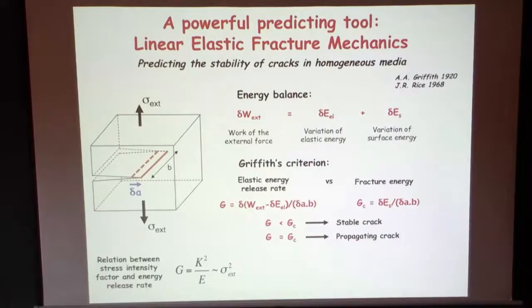Excuse me, why do you call this right hand term dissipation? I mean, if it's just creating the surface, you could regain the energy. Yeah, if we had a real surface energy, you would say, okay, I break the bond, and later on I can bring it back together and recover this energy. Practically speaking, you don't recover this energy because it's not only bond breaking, it's a lot of dissipative processes during fracture. I won't go into the detail, but you cannot heal a crack in 99% of cases. So the energy is actually lost.